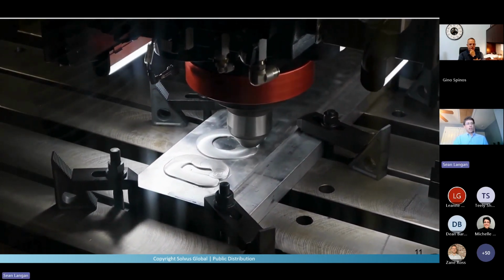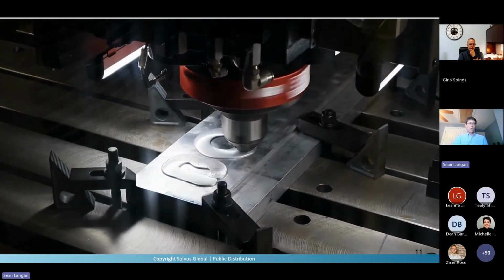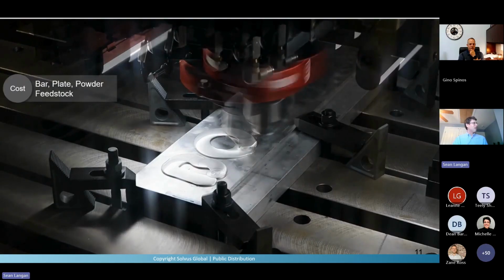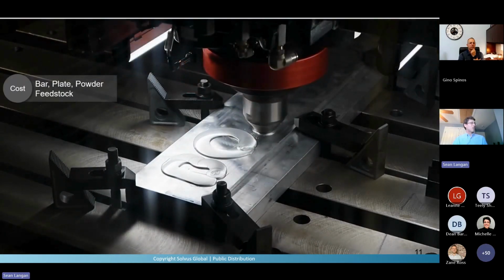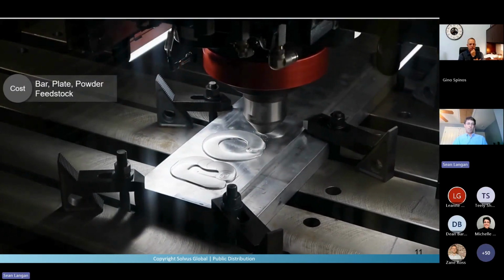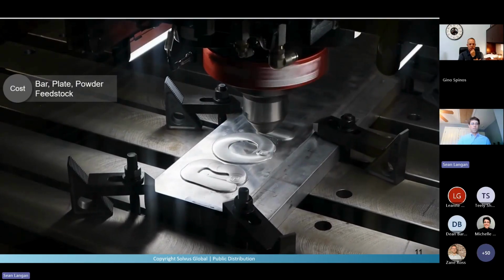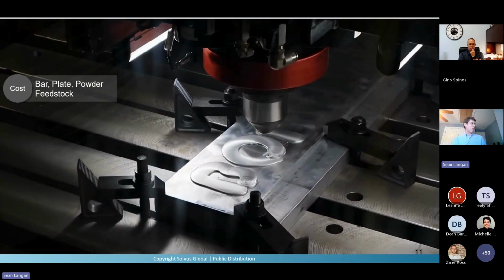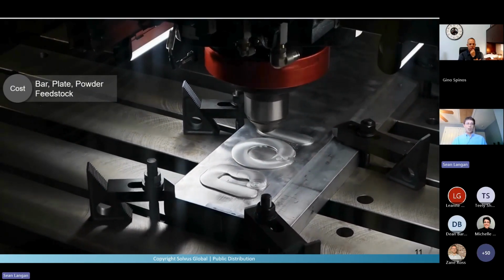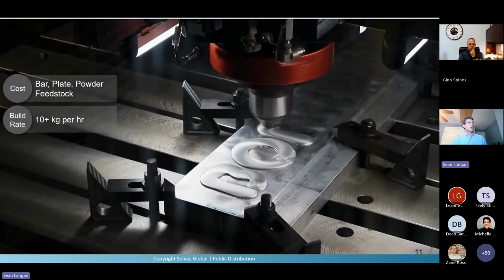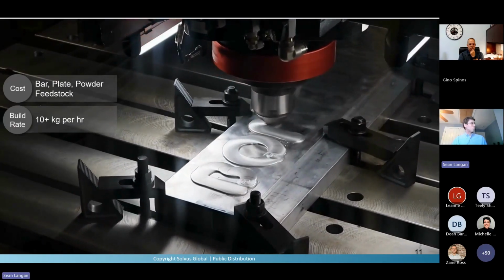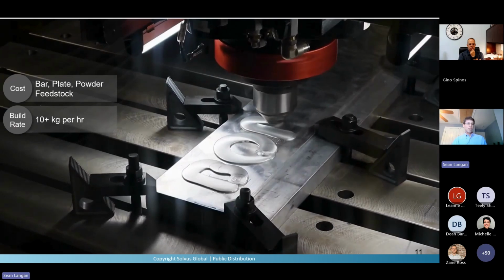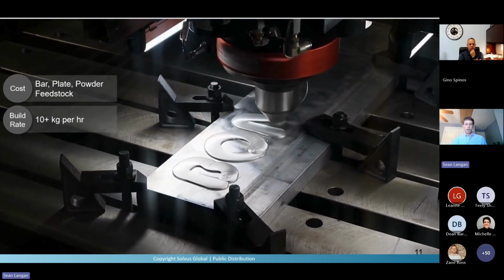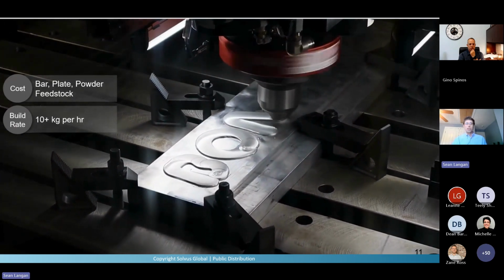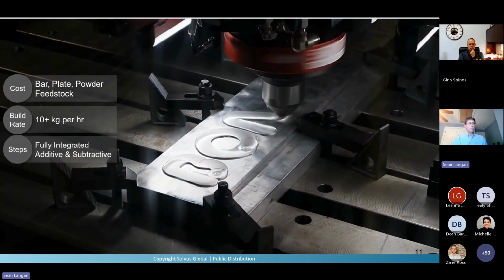It's nice because it is a solid state process. You don't have melting, so you avoid some of the heat affected zones and other problems that you have in melt-based processes. It's a low cost technology because of the feedstock, what you put in before you get your final part. We have a lot of choices in that. We can do bar stock, plate stock, or even powder. It's got a really high build rate. 10 kilograms per hour is fairly easy to hit. There have been people who've been able to hit up to 100 pounds per hour. And a fast build rate results in lower costs.